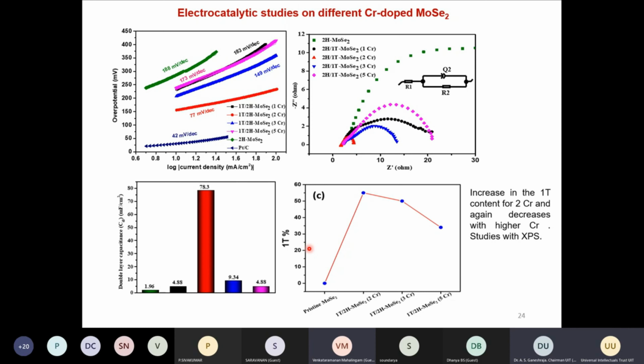And this is to understand how much of the 1T phase is present inside the material. We have done this from the XPS analysis. As I mentioned before, XPS is one of the tools to understand this 1T and 2H phase. What we observed is a higher 1T phase content, about 50% or slightly more than 50%, in the case of 2% doped chromium compared to 3 and 5% chromium. Compared to pristine, that is, the sample without chromium, it is quite high.